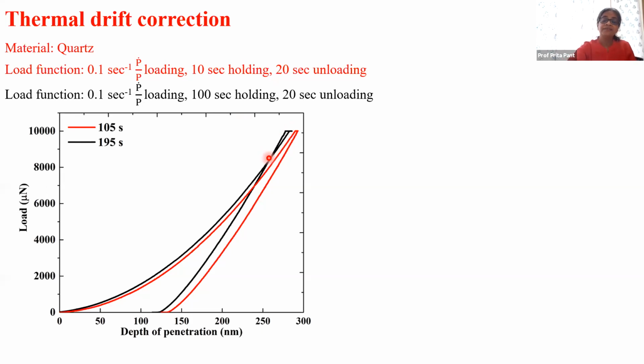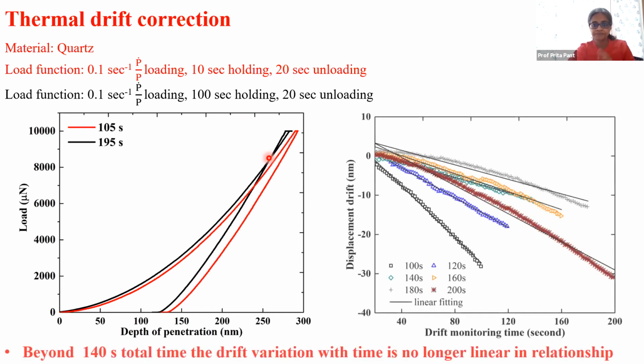The reason I'm showing you this example from quartz is that we say, okay, quartz is not viscoelastic, and it's a room temperature experiment, the labs are usually kept cold at a temperature of about 22, 23 degrees. I'm not going to have to worry about drift, but you do, and you should check.